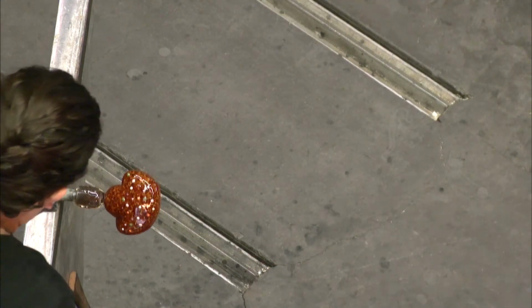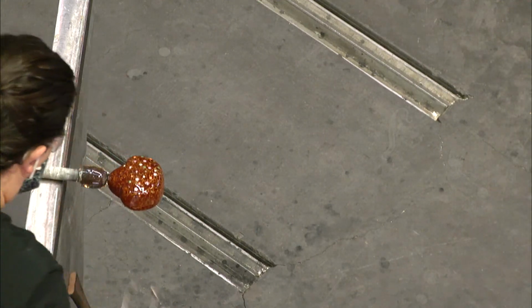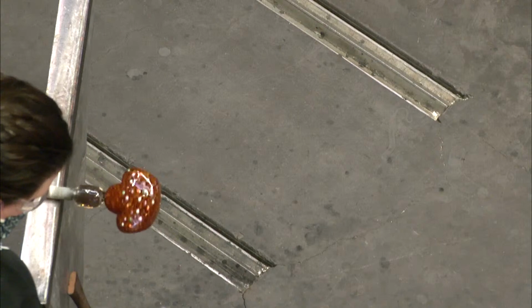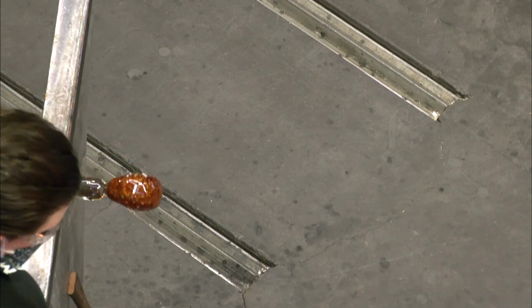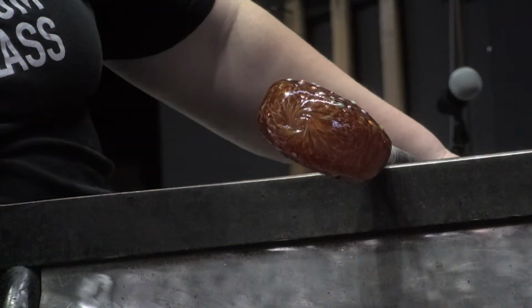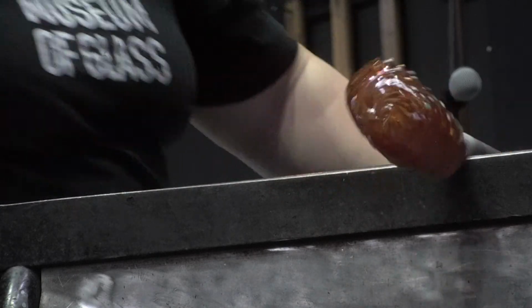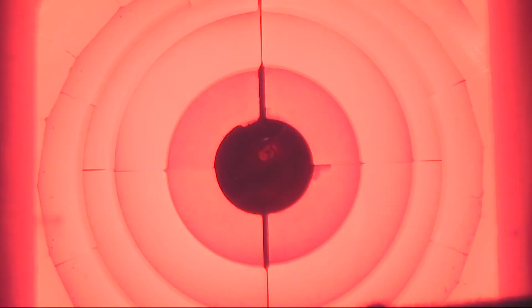So to avoid that, something you see quite a bit in sculpture with glass when it's blown is to use a tungsten pick. You don't have to have it on a drill, this just makes it a little bit faster. But tungsten's a really good material that, unless it gets really hot, won't actually stick to the glass. But when you heat it enough with a torch, it drills right through that rigid glass and makes a vent hole. So that's a smart move on her part.